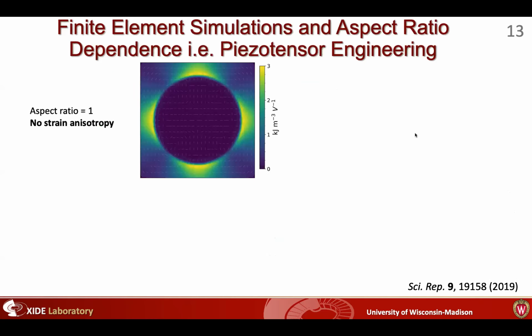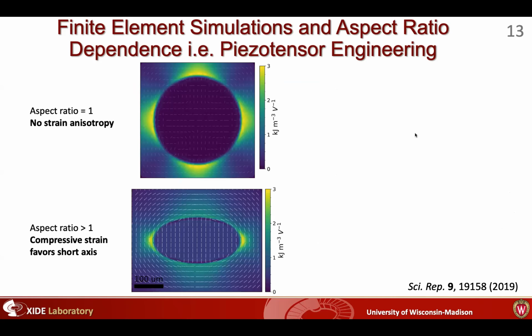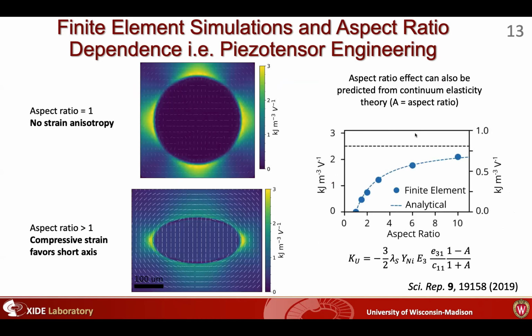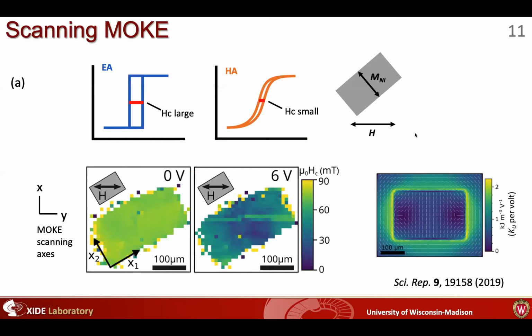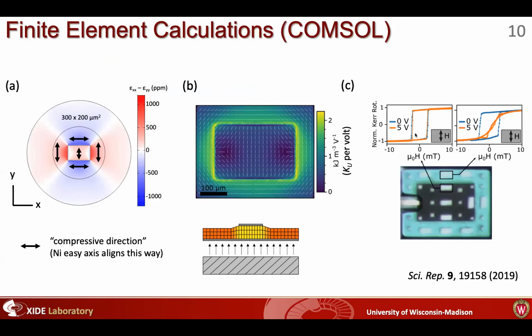And then just before we started moving on to the 011 orientation, we started to play with other shapes. And what we found was there's actually an analytical model, called the Eshelby tensor, where if you use elliptical electrodes instead of rectangular ones, you can make the area within much more uniform in the strain response. But honestly, the coolest part to me is you can see a big response just off the electrode, and then it's more of a strain gradient as it gets weaker, the farther from the electrode area.